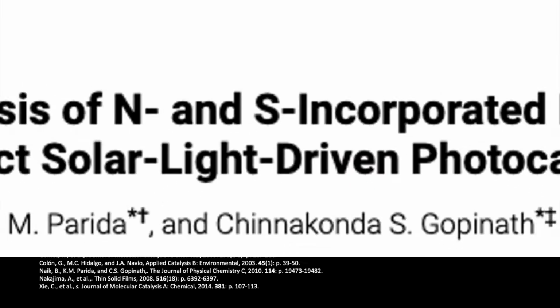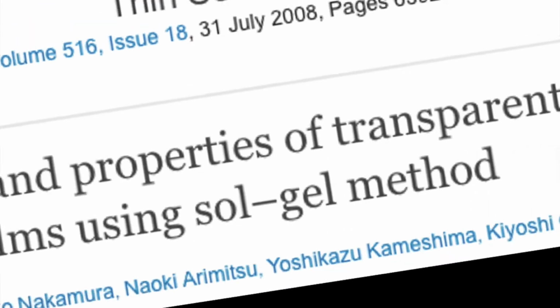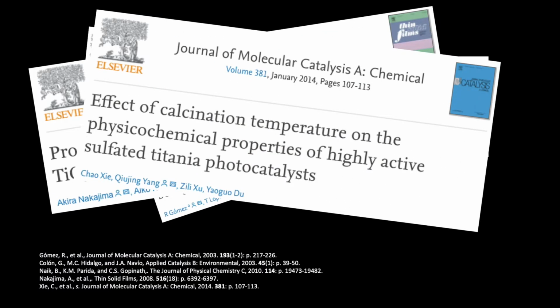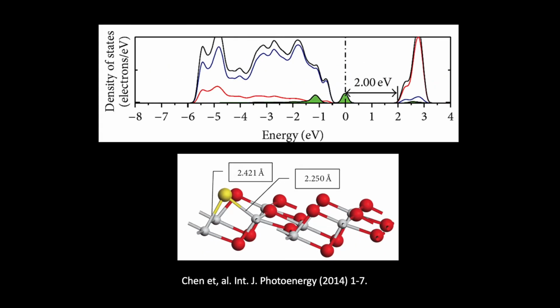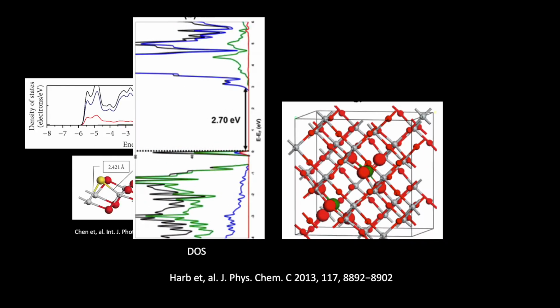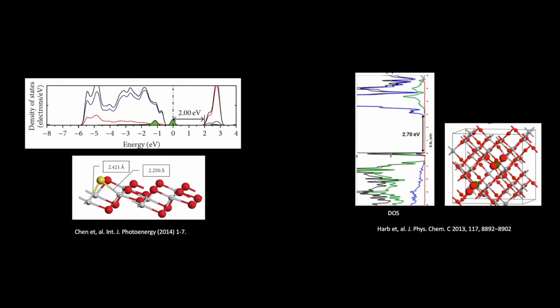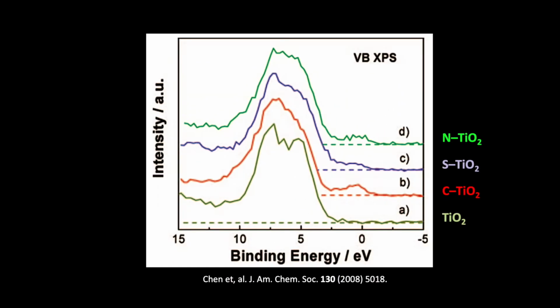In several studies, it has been proposed that doping titanium with sulfur would resolve this issue. Quantum calculations have shown that replacing lattice oxygen or titanium atoms with sulfur could create filled electronic states above the valence band maximum, increasing the Fermi level, resulting in a narrower band gap. Also experimentally, the presence of these sulfur-induced states has been shown using valence band XPS in sulfur-doped material.